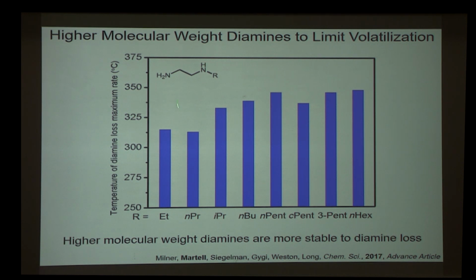On one end of the diamine, we have a primary amine, and on the other, we have a secondary, where we can vary the identity of this R group. We found from crystal structures that this diamine coordinates to the framework exclusively through the primary amine. And what we've hoped is that by using bulky alkyl groups in this position and using a higher molecular weight compound, we could minimize the volatilization and improve long-term stability. And indeed, this worked. Going from a small ethyl group up to a large N-hexyl, we did indeed limit that volatilization. Now, we need to ask ourselves, by introducing something bulky in this position, did we impact the CO2 capture?